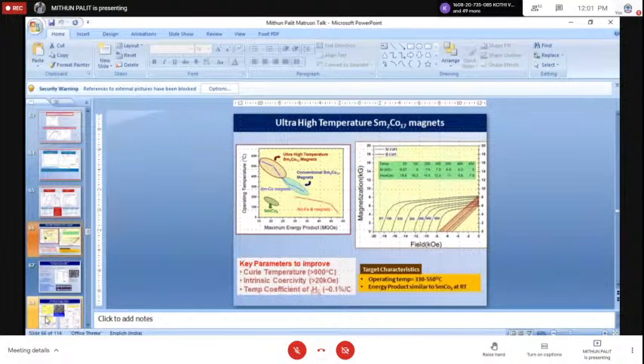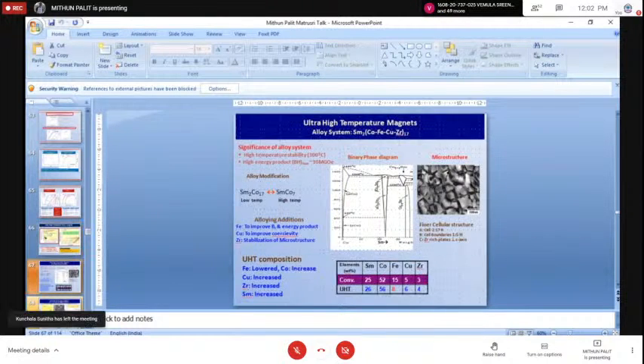Now the Sm2Co17 normal grade of magnet can be used to a maximum temperature of 350 degrees centigrade. However, there are certain high-end applications where these magnets are used in motors which have very high RPM, and there the temperature rise is very high. In those cases we use the ultra high temperature grade 2:17 magnet. There also composition optimization is important.